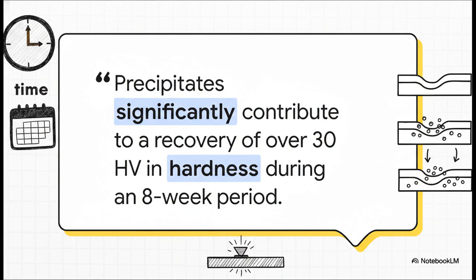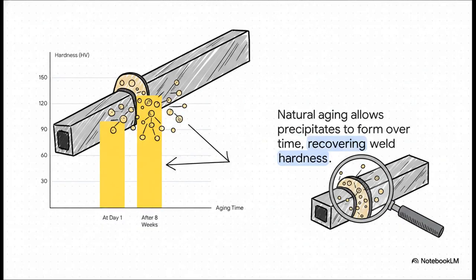There's this phenomenon called natural aging, and as this quote points out, sometimes just letting a certain type of aluminum weld sit around at room temperature is enough for those precipitates to form all on their own. You can see it right here on the chart. The day after welding, the hardness is at a certain level, but then you just wait. After 8 weeks, the hardness has shot up significantly, and it's all thanks to those precipitates slowly but surely locking the microstructure into a stronger and stronger state. The metal is literally strengthening itself over time.